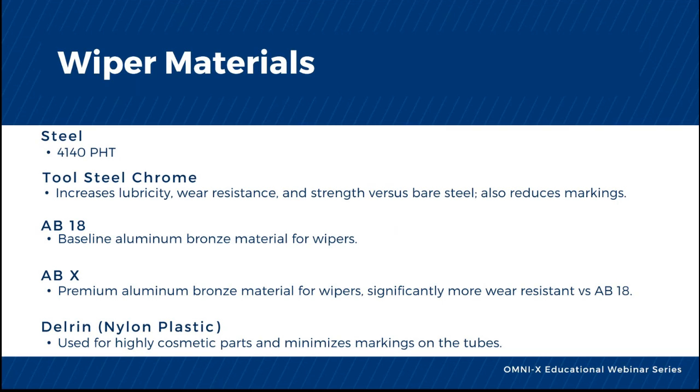4140 is the generally recommended steel for wiper dies. Using a steel wiper die with chrome plating helps to increase lubricity, wear resistance, and strength of the wiper. Chrome wiper dies also reduce markings on the tubes.